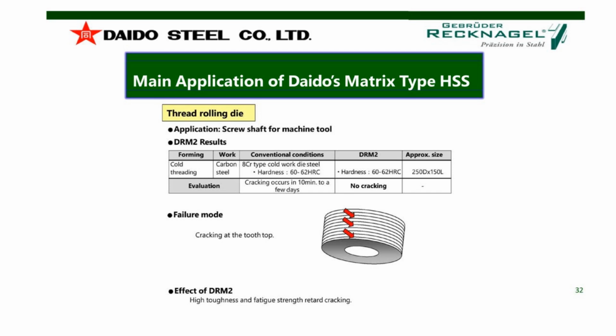As I told, thread rolling dies are very special because normally you always have a problem with cracking of the tooth top. This is the main failure with thread rolling dies. In this case, the customer was first using a typical 8% chromium steel with a hardness of 60 to 62 HRC, and the failure mode was early cracking after some minutes or a few days. Then he tried DRM2 for the first time with a hardness of 60 to 62 HRC, and he has no cracking.